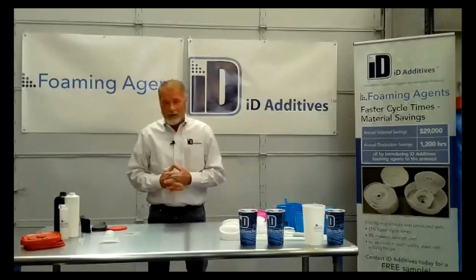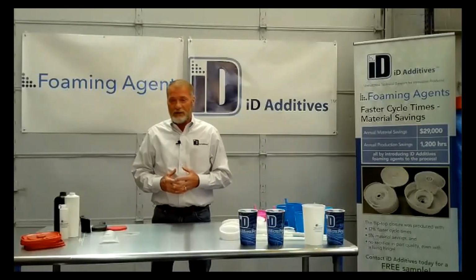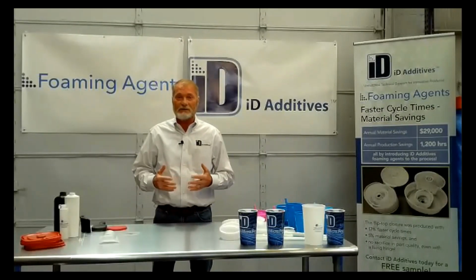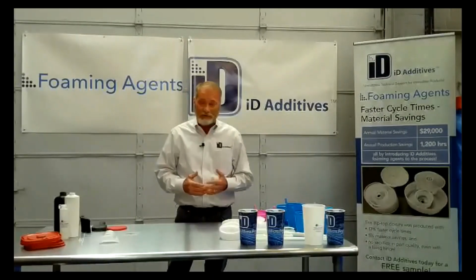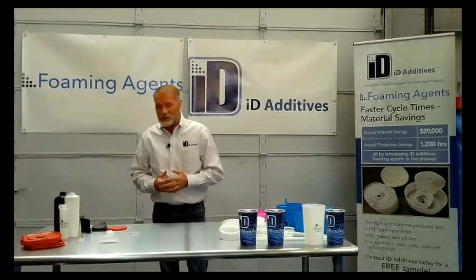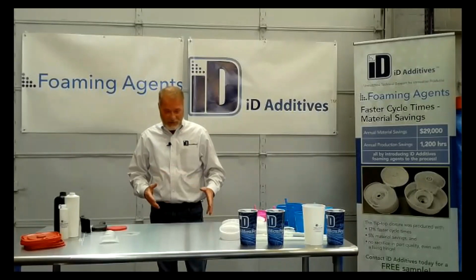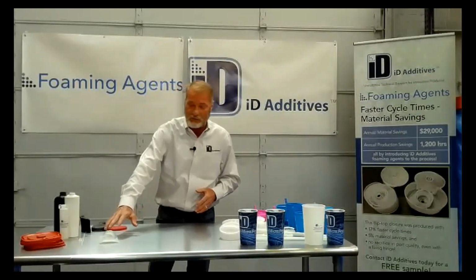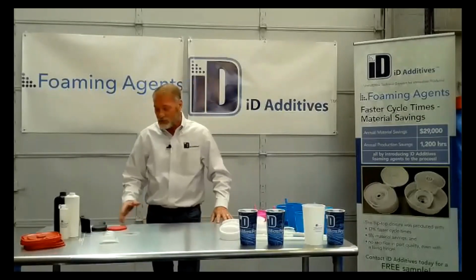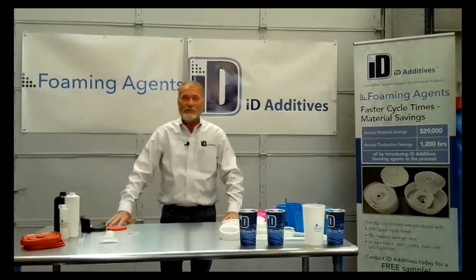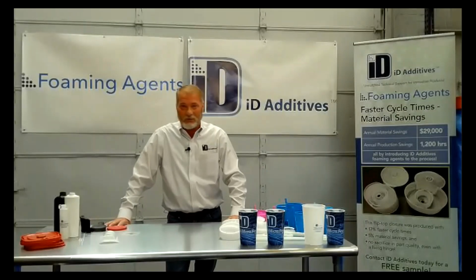So in extrusion profile, exothermics tend to work the best, or maybe an endo-exo hybrid. When it comes to sheet extrusion, endothermics perform extremely well. And we do have samples of sheets and stuff right here that we're done with endothermics. Extrusion blow mold would be endothermic, injection molding, structural foam, low pressure machines. It's all endothermic foaming agents. Rotational molding would be an exothermic.